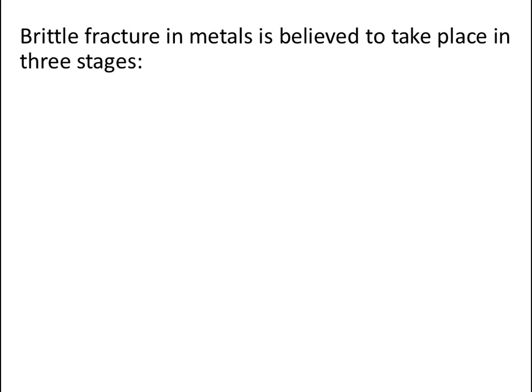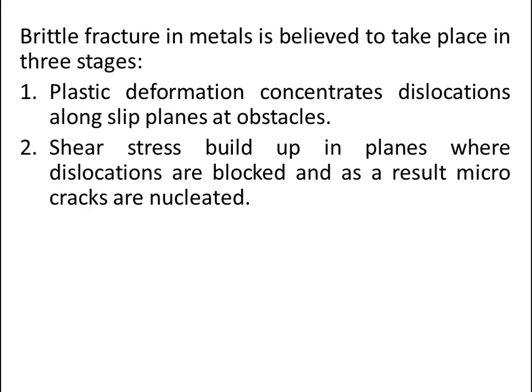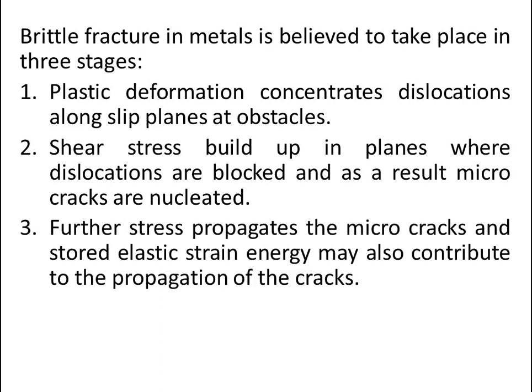Brittle fracture in metals is believed to take place in three stages. First, plastic deformation concentrates dislocations along slip planes at obstacles. Second, shear stress builds up in planes where dislocations are blocked, and as a result micro-cracks are nucleated. Third, further stress propagates the micro-cracks, and stored elastic strain energy may also contribute to the propagation of the cracks.